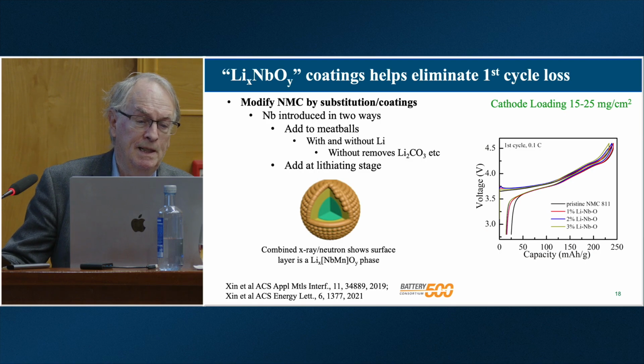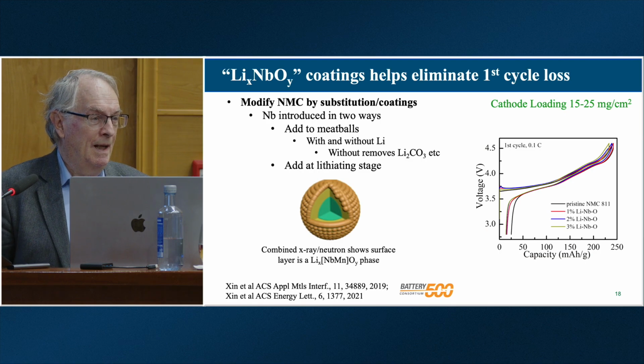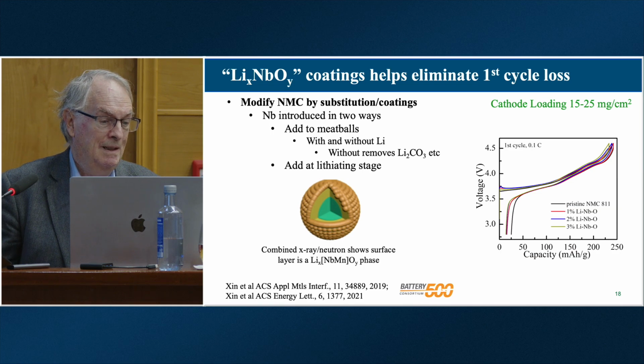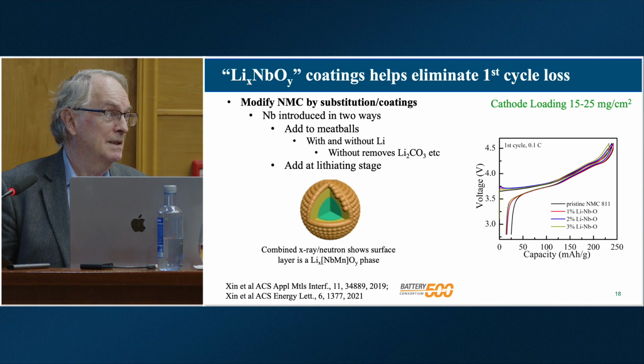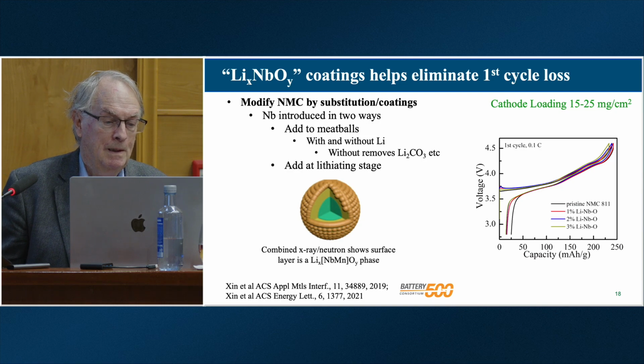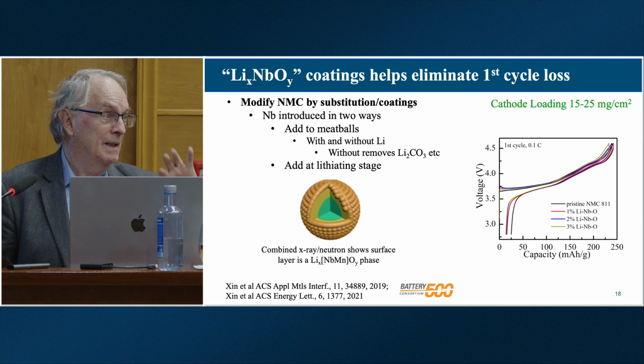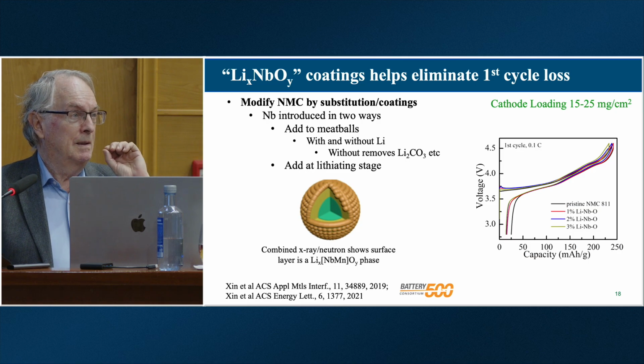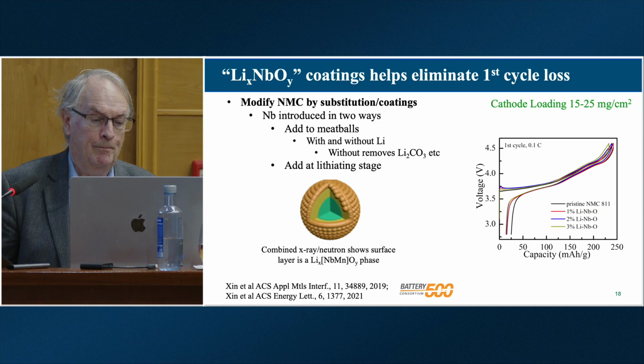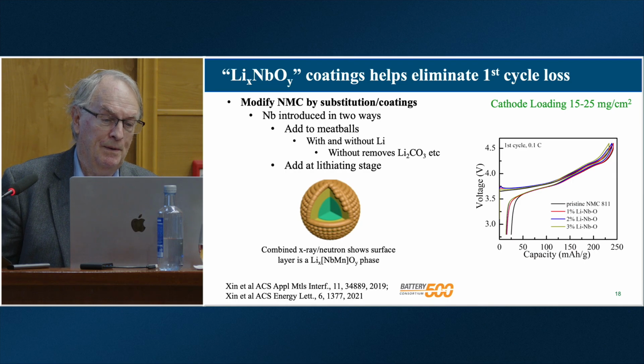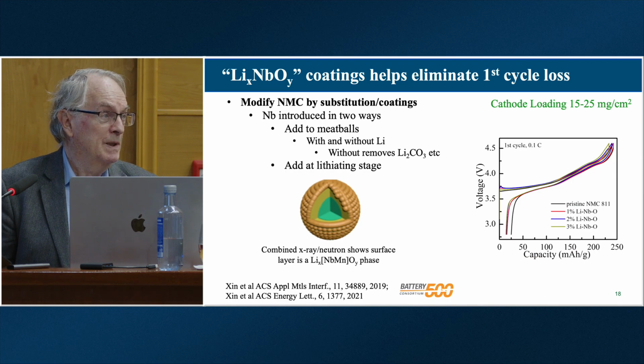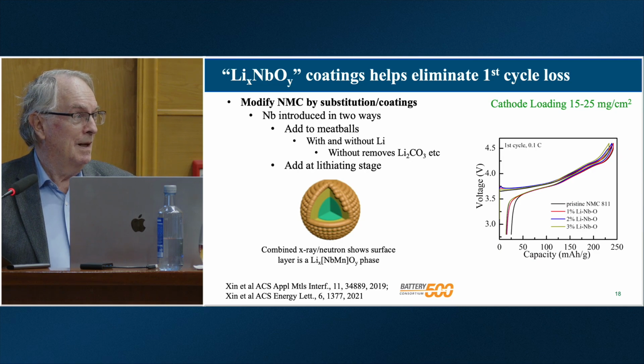So what we did is take our meatballs, we then immerse them in a solution of a lithium niobium ethoxide. So soak in, then we fire these meatballs up. Depending on the temperature we fire at, we can get a coating on the outside, or niobium goes inside the structure. And you can see from that plot there, just 1% niobium, we can eliminate half this first cycle loss at room temperature. As we do the characterization of these materials, it turns out much more complicated.